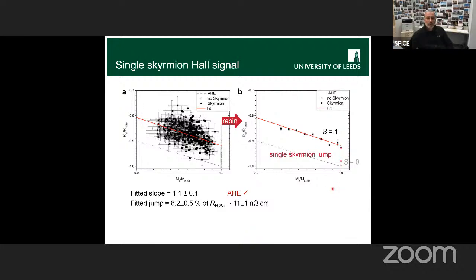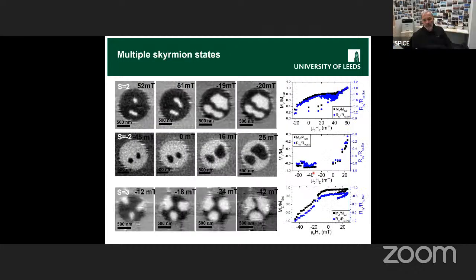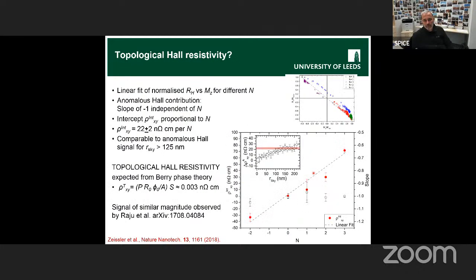So you could just say that's the topological bit because there's a change in topology. But it's not quantitatively consistent with the Berry phase theory. Well, I will have to look at the numbers. As long as you have a finite number of skyrmions, and you're sampling only one skyrmion through the sample you're measuring, then the topological Hall effect should be proportional to the gradient you've experienced, because that's the effective orbital field. Yeah, that would be this graph here.